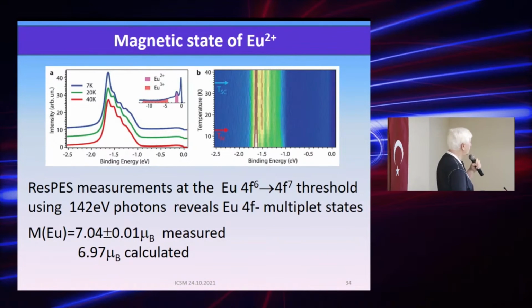The first, what is seen here, is that nothing happens at superconducting temperature. So again, the superconductivity onset doesn't affect the magnetic state of europium. Second, these measurements indeed confirm that the europium is in the expected state, and the magnetic moment is 7.04 Bohr magnetons, and it is nicely consistent with the calculated 6.97 Bohr magnetons. But the picture shows that indeed, as you go to the magnetically ordered state, the spectral weight here transfers to the ground state, and the lower states of europium are almost out of game and do not affect anything here.